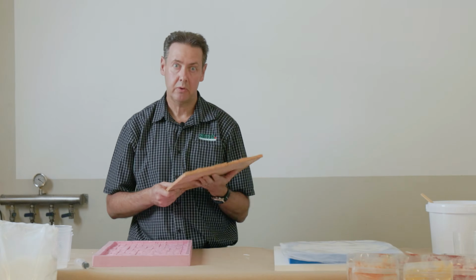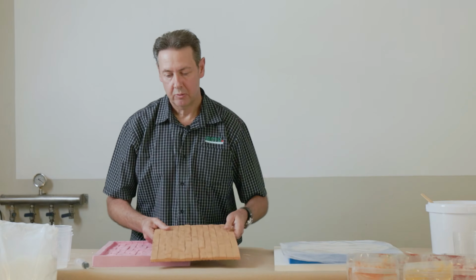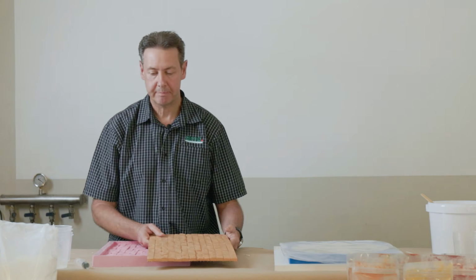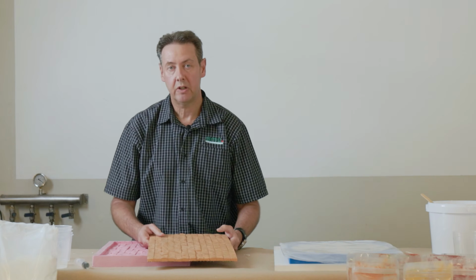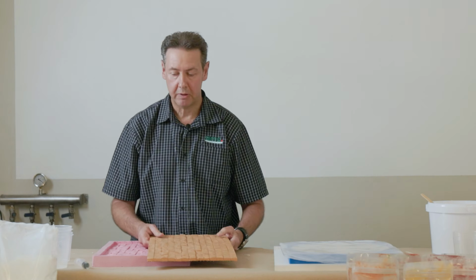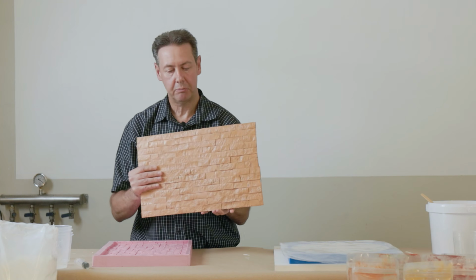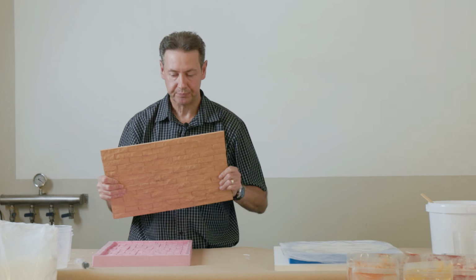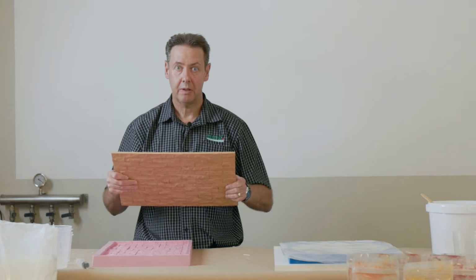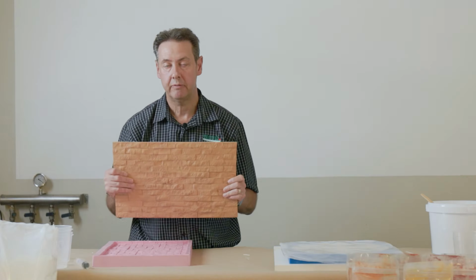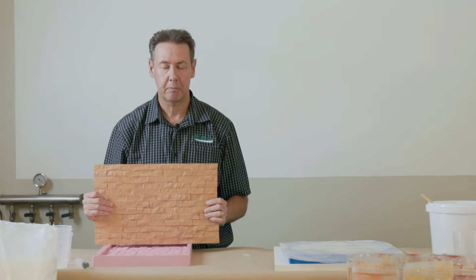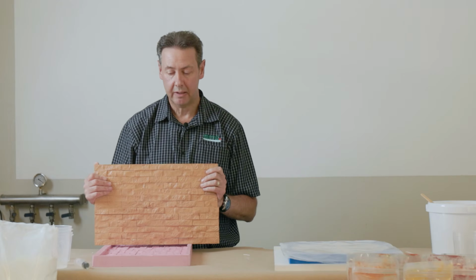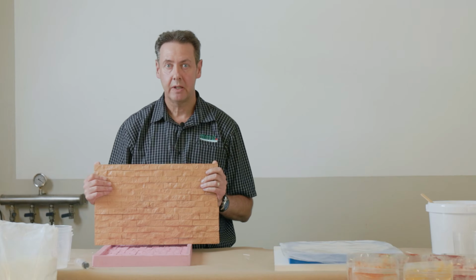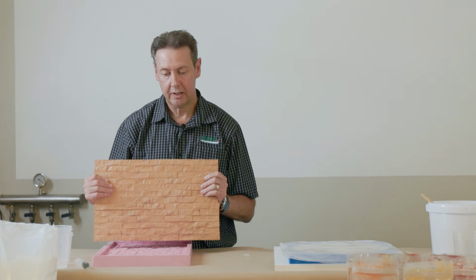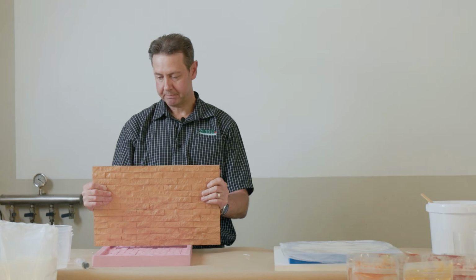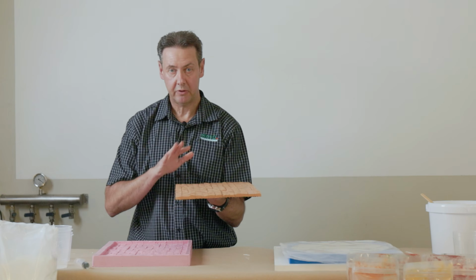But there's many other things that you can do with GFRC. You can do wash basins, you can do fireplace surrounds, outdoor furniture, you can do planters like pot plants, keeping your material nice and thin but super strong. As mentioned, very important through this process to use alkaline resistant fibers. If you use standard glass fibers, they will break down in the alkalinity. The alkalinity will attack those glass fibers and it'll start to corrode them, and you can have those panels failing. But if you're using alkaline resistant glass fibers, it's perfectly good.